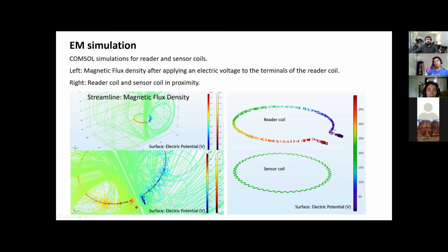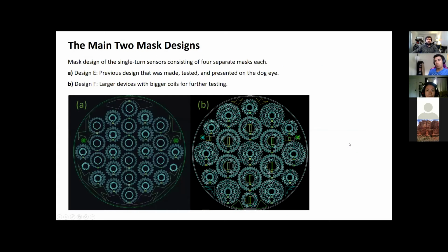What we got quantitatively from the simulation was the value of the inductor, which really fit with what we were anticipating, which is around 50 nanohenries. 50 nanohenries is about what you get from a coil that is 1.4 centimeters in diameter. And that was nice to verify with simulations. Here, I'm showing two main masks that I use. This is the first generation of devices we made, and then we also made larger ones to compare. I'll talk more about them next.